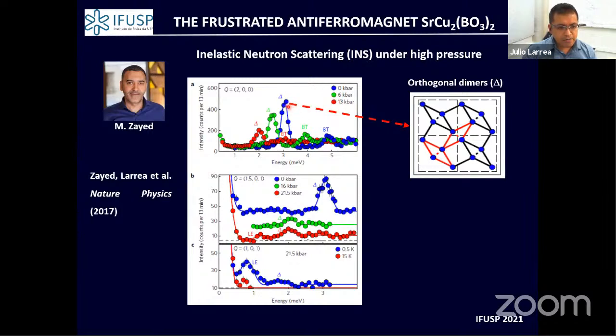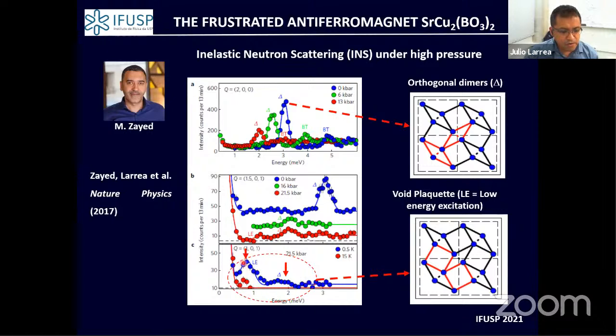With the application of pressure, what you are seeing here is that pressure tunes the gap to lower energies, right? At a pressure close to 21 kilobar, in addition to this excitation of the gap, another excitation appears at much lower energy. With the help of theoreticians, we explained this new energy scale at lower values as a signature of the plaquette phase. This was the first experimental evidence of the existence of this entanglement of dimer states.